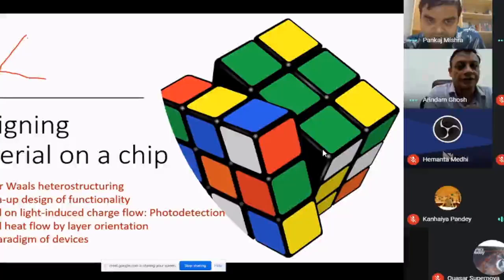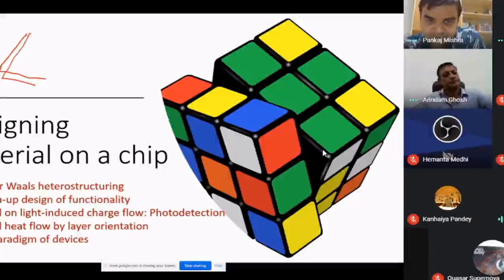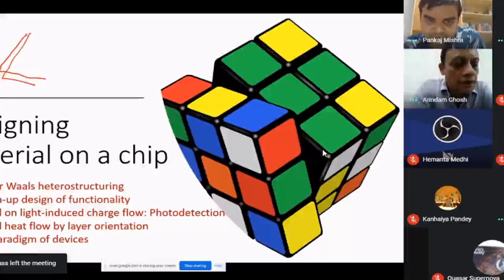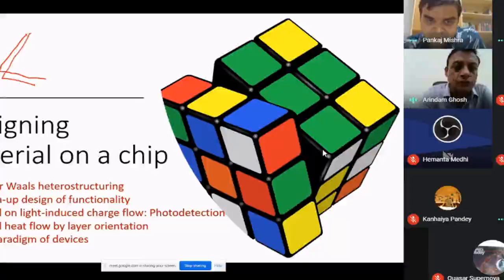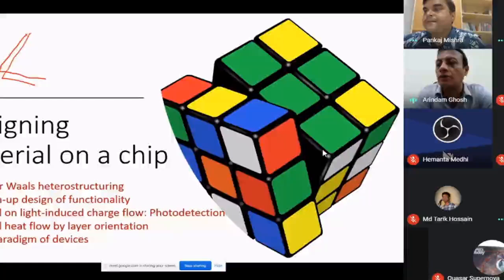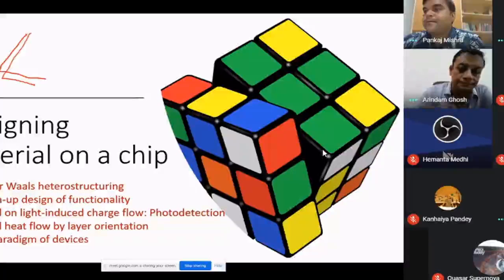Is there any calibration? Like, for example, from Raman, can I say that there is a twist, as that is the standard technique for determining number of layers? Yes, you can, but for that you need to have these shear modes. If you know the shear modes of this twisted bilayer of MoS2, you can tell the angle. But if you don't have a Raman spectrometer which goes below 50 inverse centimeters, you cannot measure the shear modes. Low frequency. Okay, so shear modes give you the angle. Okay, thank you.